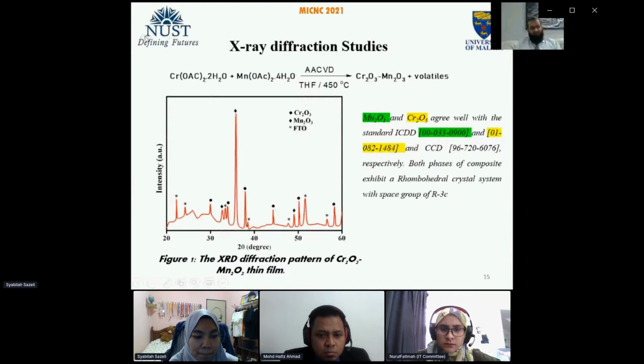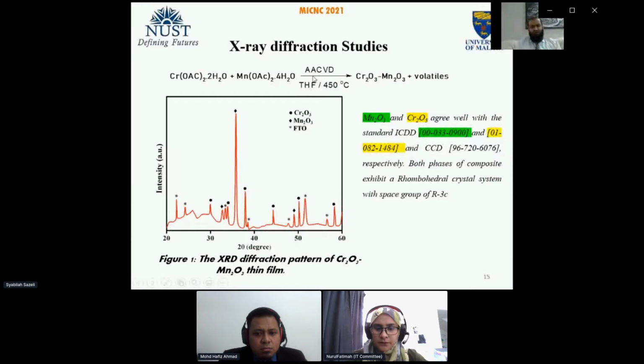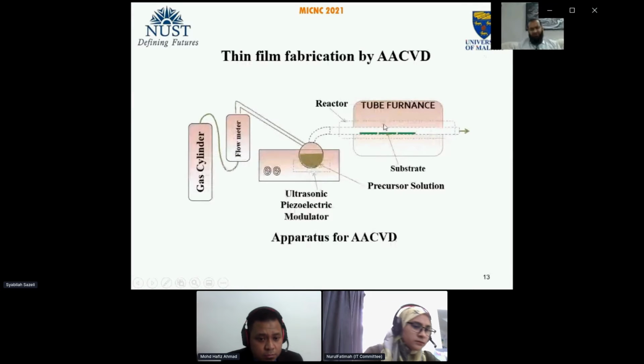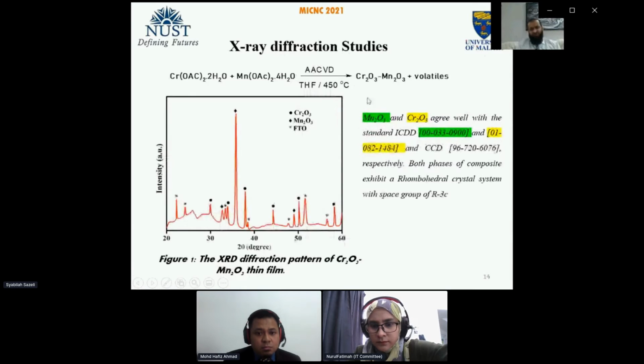The current material, the chromium and manganese composite oxide thin films, were prepared from chromium acetate and manganese acetate solution dissolved in THF, and the AACVD was performed at 450 degrees centigrade, and the volatiles escaped. After the films were generated, like here I have shown, these films are basically coated with our material, chromium manganese oxide. These were then subjected to characterization.